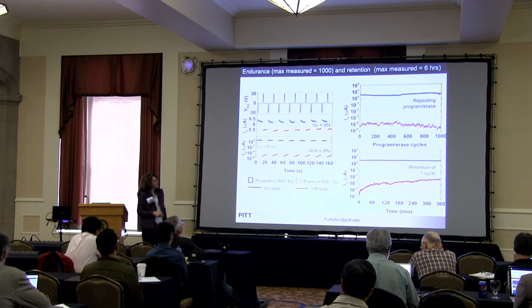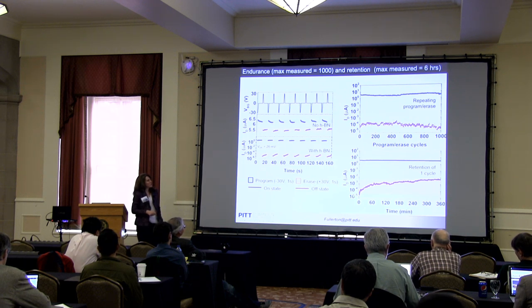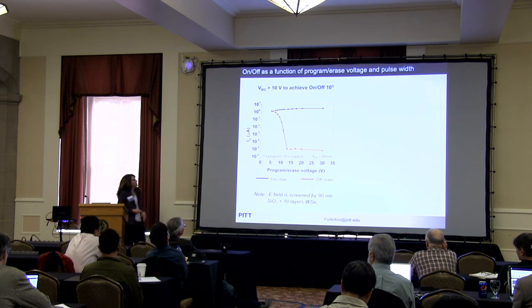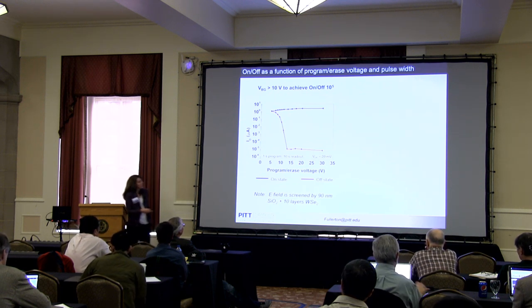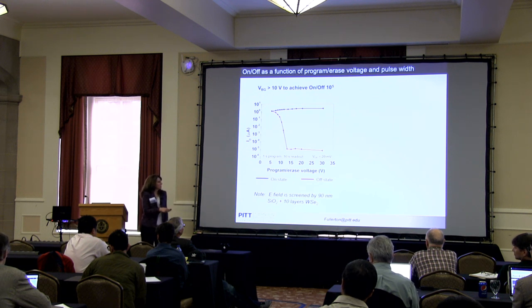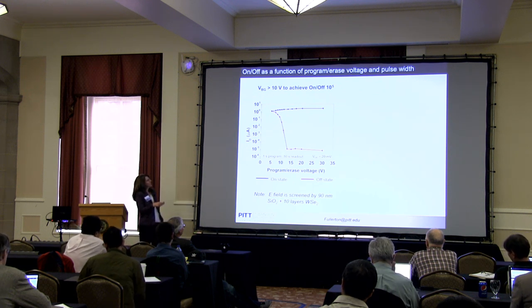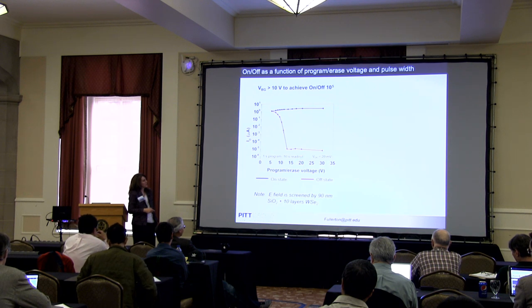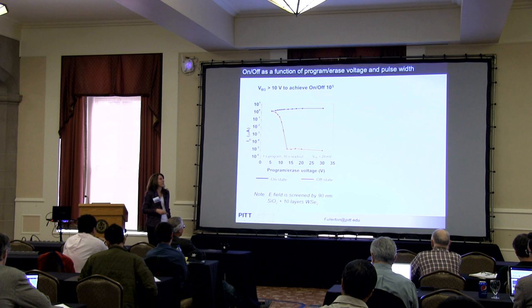Yeah, so we could walk to column two of the periodic table. And I think what some of the DFT calculations on these metal crown ether complexes show is that once you remove that second electron, now the ion complexes even more strongly with the crown. So what you've done there is increase the energy barrier to switching. You might say, oh, that sounds bad, but maybe it would be good to have a distribution of energy barriers, because then you could think about multi-bit storage, right? You apply some voltage and you switch some, and you apply another, higher voltage and you switch some more. This is way out there, but that's the type of barrier engineering I envision us doing, and now we have some more money to do the synthesis of those molecules.